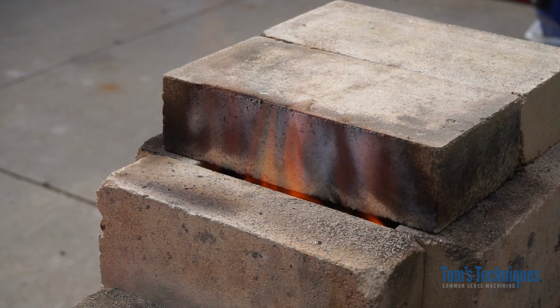So that'll probably burn easily another 20 minutes or a half hour. And that part, I guarantee, if you can see in there, is red hot inside. And that part's probably red hot too. So it's soaking up the carbon. I want to keep it at that temperature for at least 45 minutes. So I'll let this batch burn down, and then I'll add one more batch, and then we'll open it up and quench it. Hopefully we'll have nice hard parts.